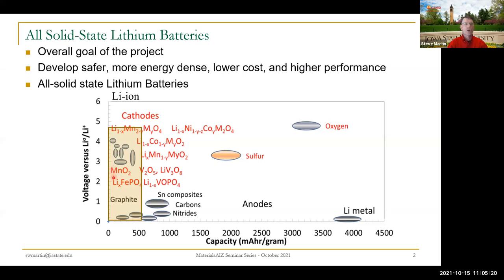Cobalt was an early starter in this area, and they reduced the cost and increased the capacity by making these mixed manganese, nickel, and cobalt hybrids. But still, the capacity is relatively low because it takes a lot of transition metal and oxygen to store lithium, and it takes 6 carbon atoms to store 1 lithium atom. They're very safe, they're very functional, and they go beyond the energy densities we could attain from nickel metal hydrides and lead acid, but these batteries are still quite hindered in their capacity.